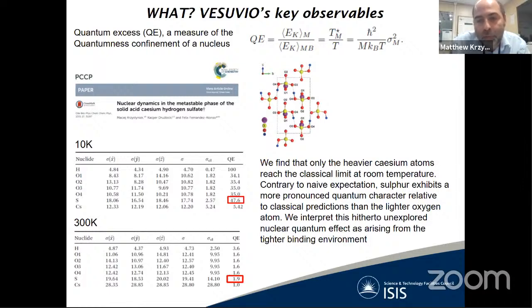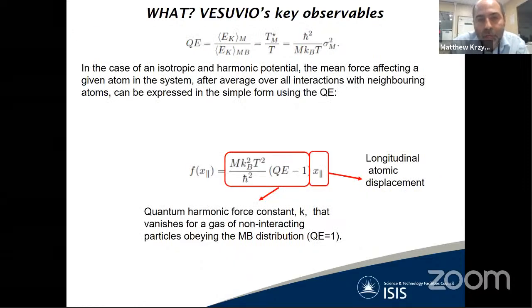And we interpret this quite hitherto unexplored nuclear quantum effect as arising from a tighter binding environment, which confines the wave function of the sulfur in this material. And this would be the nuclear kinetic energy of confinement, which is quite important in current studies of metastable systems like glasses. Another nuclear quantum property that can be related to the quantum excess is the quantum harmonic force constant of the mean effective force that is acting on a nucleus in a solid-state system. And it can be shown that this quantum harmonic force constant would have been zero if it wasn't for the fact that we have a quantum excess.